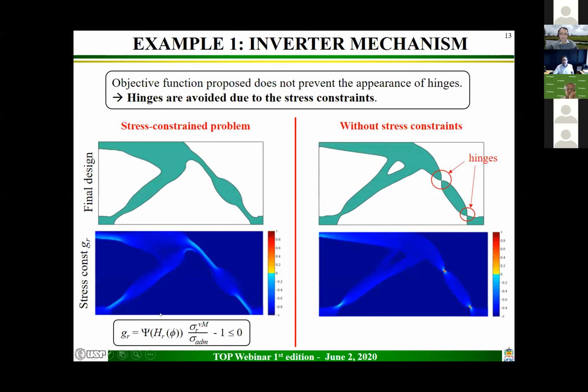So we have solved the problem considering stress constraint and without stress constraint. When you consider the stress constraint, we come up with a hinge-free design where the stress constraint is satisfied. When we do not consider the stress constraint, we come up with hinges and stress concentrations. So it shows that the objective function proposed does not prevent the appearance of hinges. Hinges are avoided due to the stress constraint.